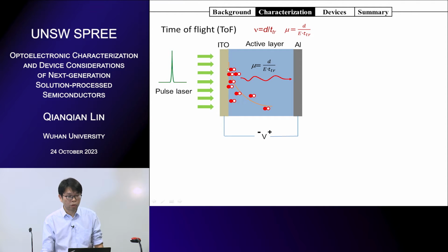And the carriers could be drifted under the bias voltage, and we can easily measure the thickness of the active layer, and we can also record how much time it needs for the carriers to reach the counter electrode. And we know the distance and the time, so we can get the velocity of electrons. And if we also divide by the electric field, then we get the mobility.